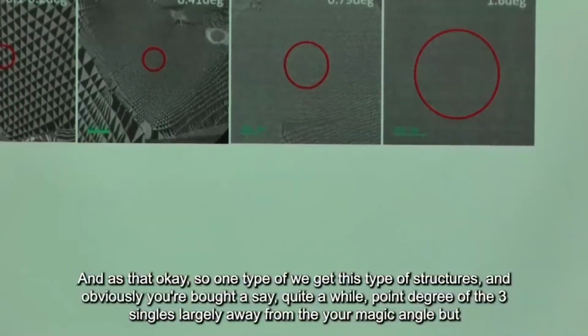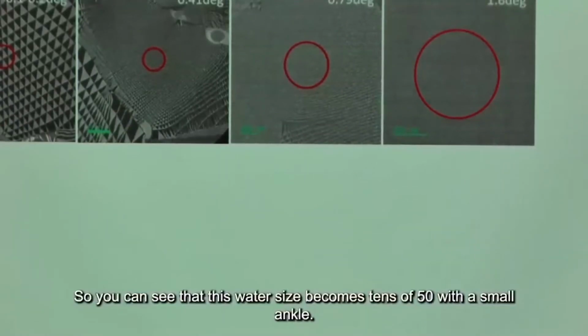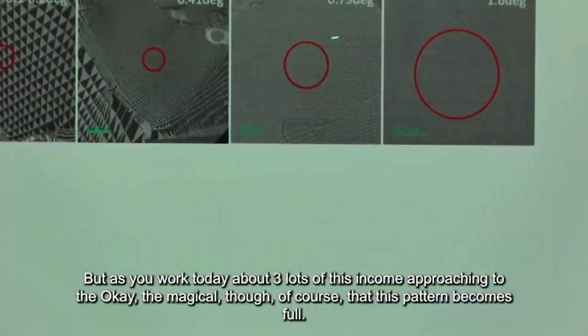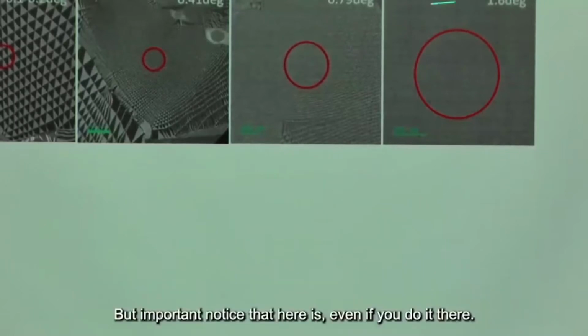Say 0.1 or 0.3 degrees of twist angle, largely away from your magic angle, your moiré size becomes larger, and the scale here is about 200 nanometers, if I calculate it really carefully. So you can see that this moiré size becomes tens of nanometers, even 100 nanometer length scale with a small angle, right? As you go to a larger twist angle, approaching or passing through the magic angle, then of course this pattern becomes small.